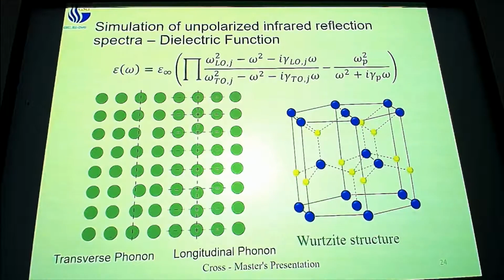So the dielectric function here, and there's actually two of these, one for the perpendicular polarization, one for the parallel polarization, has these terms, omega LO and omega TO, which correspond to the longitudinal and transverse phonons. Now, if you look down here, most of you should know this, but there might be people watching who don't, are the shifts of the atoms or the molecules from their actual position. So if I have my atoms lined up in a row like this, where that dotted line is where they should be, a transverse phonon shifts them away from that line, perpendicular to that line. A longitudinal phonon shifts them in the same direction as that line, so that they compress between them and increase the space between them.